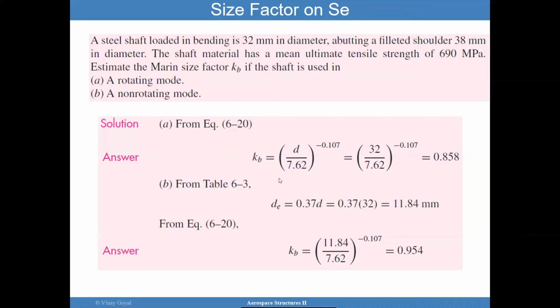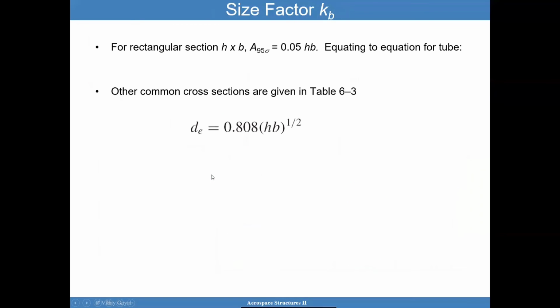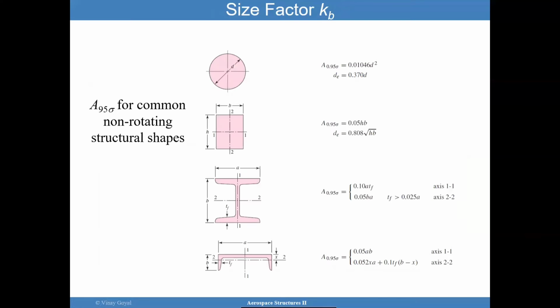For non-rotating mode, I'll then use 0.37 times D. I get 11.84 and I plug it in and I get a Kb of 0.954. So again, I want to make sure I consider the correction for non-rotating situations. So these are for non-rotating. All these De values are for non-rotating.